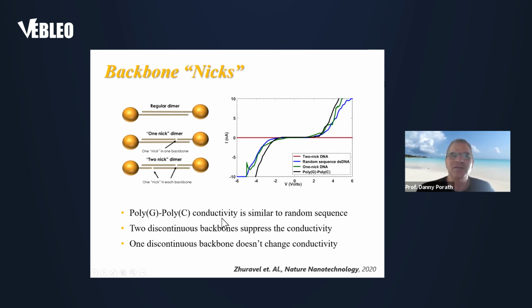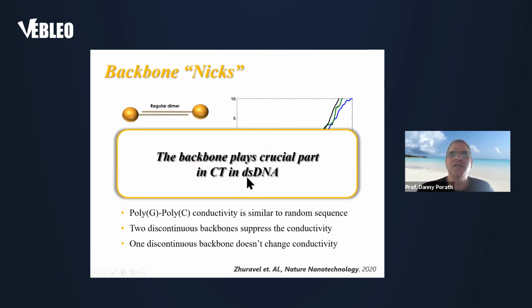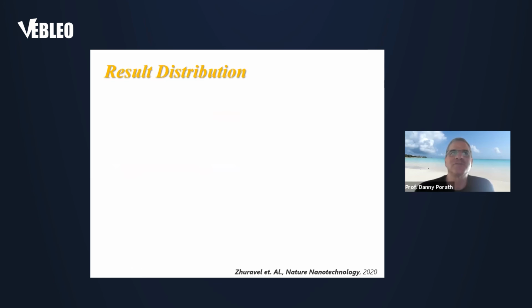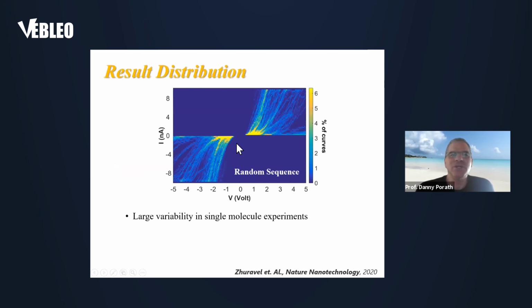So that means that the backbone plays a crucial role in the transport, and even a single discontinuity in one of the strands collapses, suppresses the current. So when we look at all the data, and here you can see all the data except for the 0 in order to avoid a lot of yellow here, we can see that there is some variability, which is not surprising when you measure single molecules.